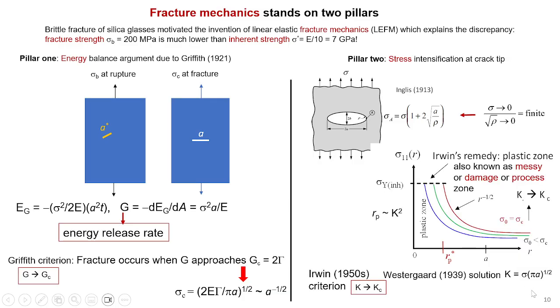So Irwin comes in and says, oh, no sample can go to infinity when the stress is infinite. Therefore, there must be some way to cut it off. So I will not go into that detail, except you recognize there are 2 pillars. One is to emphasize the stress can build up through the far-field load, K. The other one is the condition for the crack to occur by looking at how the energy can accumulate and be released to pay for the surface tension you create. So in doing that, they have identified the relationship between these 2 quantities and described fracture mechanics either in terms of a critical K or a critical G.